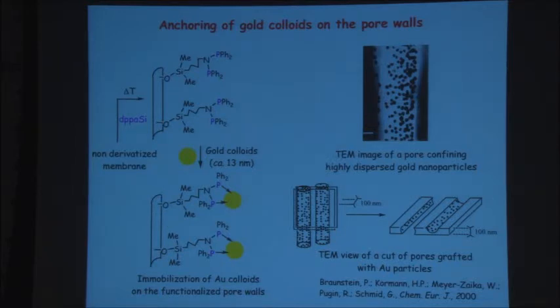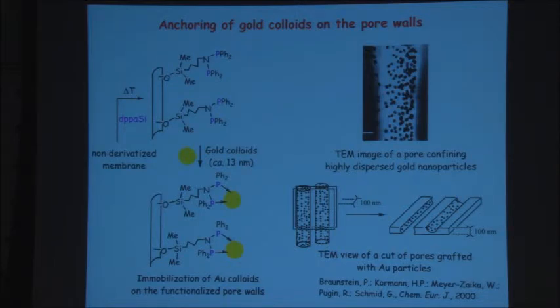We take the membrane, this alumina membrane, that we react with our ligand to form the diphosphines here, which are pendant. We first tested the concept by using gold colloids, which can be prepared in a very reproducible manner since Faraday, 13 nanometers, and we could actually see that the gold colloids are immobilized into the channels of our cannellonis. So you can wash the cannelloni, what has been hooked up by the chelate remains there. Then you can open by a microtome system, you can cut the pores here and look by TEM at what is inside. The particles here have exactly the same size as the precursor. So this is a very soft approach. You have not coalesced the particles into big ones. So this system is a viable approach.